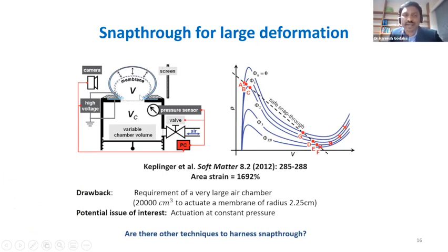What they did was put this type of balloon on a very large volume chamber, so that the pressure versus volume curve follows the gas inside this chamber, the ideal gas law. So there is a PV path corresponding to this variable chamber volume, so that you can achieve a snap-through such that the next stable state still falls before the dielectric breakdown. And what this helps us achieve is that we can realize this large volume state at which the dielectric breakdown still does not happen.